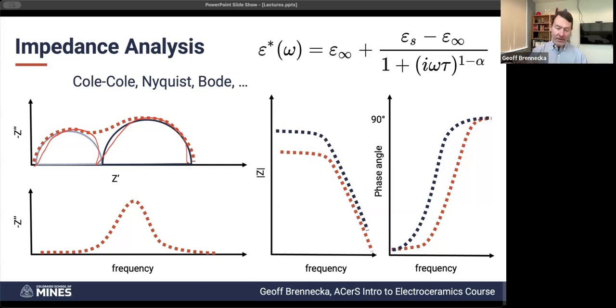Sometimes they'll start to overlap. The orange lines on here are meant to represent the actual data that are measured. And then the semicircles are what you've built up: a circuit where you say, here's a capacitor and I have a resistor in parallel with it, and here are the values of each of them, and it's going to give me this kind of semicircle. And then I have another polarization mechanism that's a separate portion of the sample. Maybe this one represents the grains and the other one represents the grain boundaries.